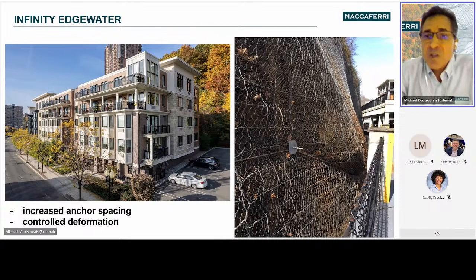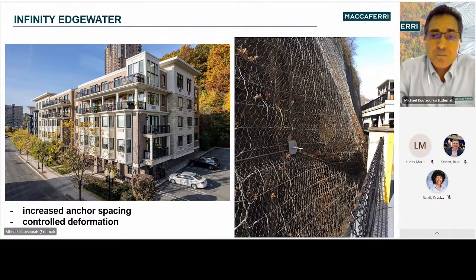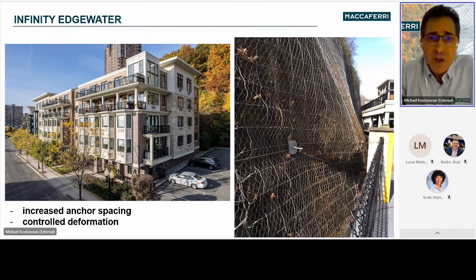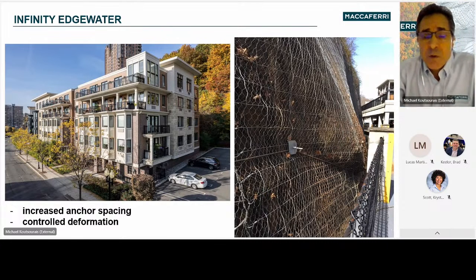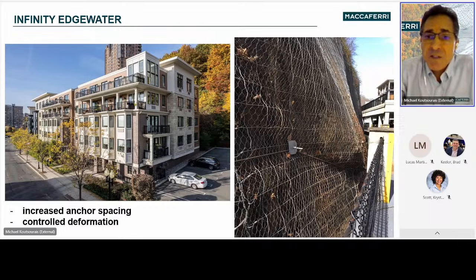A composite cabled mesh product was chosen for its high strength and ability to mobilize its strength within the deformation tolerance of the project site, while still allowing for an increased anchor spacing. In this case, the interior anchors were spaced 50-foot vertical by 20-foot horizontal. As you see here, the mesh was loaded with 2 to 3 cubic yards of rock and performed as designed, controlling the rock to about 4 inches away from the parking structure. This further emphasizes the need to consider the maximum acceptable deformation of the system on the proximity and sensitivity of nearby structures.